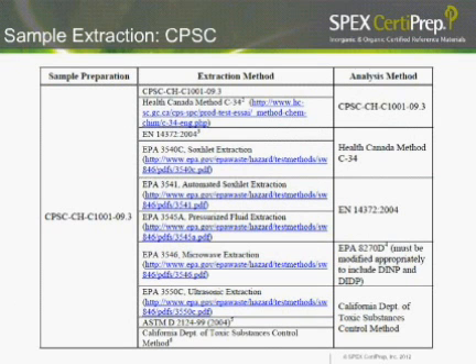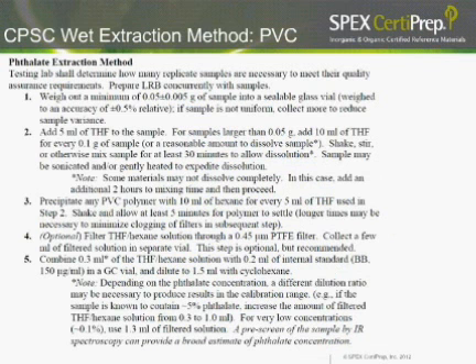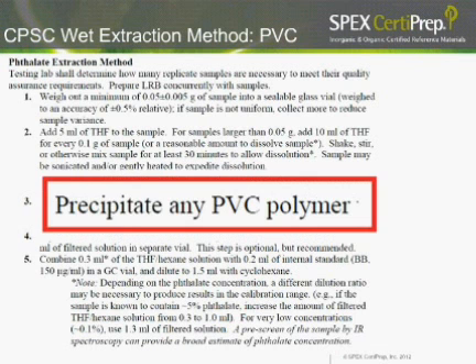Our next step was then to go to the prescribed method, the Consumer Product Safety Commission method, and choose a method for extraction. You have quite a few choices if you're following this method. You could be doing an Soxhlet extraction or an ultrasonic extraction or a microwave extraction. There is also a wet extraction method prescribed within the Consumer Product Safety Commission method, but this method is very polymer specific, and speaking with some of our customers, they've had a hard time because they did not realize that this method, if you look in the text of it, says to precipitate any PVC polymer. So this method really works only with the PVC materials to get the result that you're looking for.